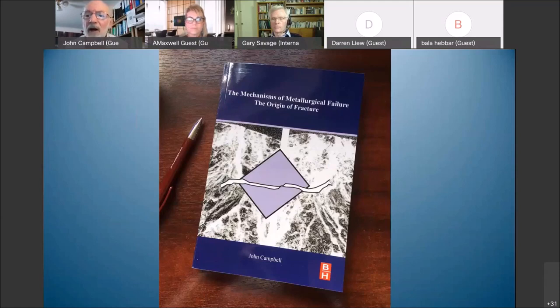But these carbides had big displacements in the matrix when they formed, and so there was a lot of dislocations formed around them because of the accommodation with the matrix as they plastically worked the surrounding matrix. And it was thought that those strain fields and the population of dislocations would be better sinks for hydrogen. So this particular steel would be able to absorb more hydrogen without the hydrogen forming itself into cracks, because it was simply disappearing down into sinks. Now, this is potentially a very interesting and useful idea.